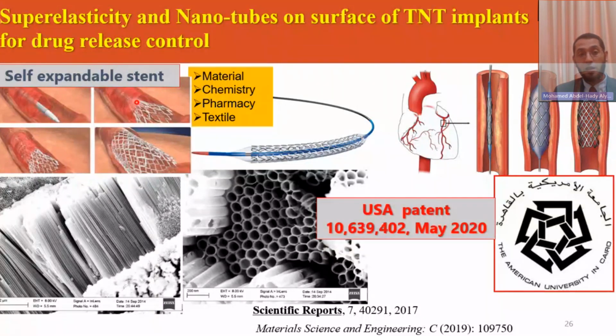So it's located there at the vein or artery that has a problem, and then by itself it expands. Not only this, actually, the material itself is very unique, but we also did some surface functionalization. So we create nanotubes on the surface of the stent itself. And these nanotubes, as you can see here, this scale is 200 nanometers. So these tubes are around 30, 40, 50 nanometers in diameter. In these tubes, we can fill the needed drug, and after implantation, these drugs are released, to make a local treatment of the affected place.